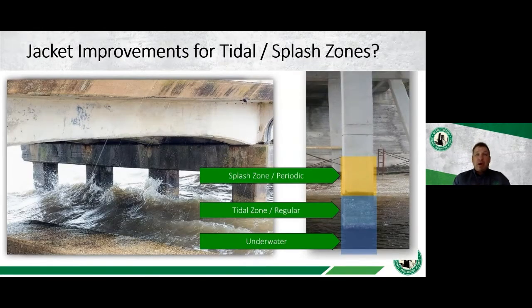By providing this type of an improvement and getting it higher, we can then provide actually protection. So not just to that tidal zone, but then we can also provide protection to that periodic splash zone where, you know, it's not wetted and it's only wetted occasionally. So if we can provide a jacket that can actually provide more galvanic current higher up, we're going to get an added benefit of basically extending the cathodic protection, that galvanic cathodic protection, higher up.